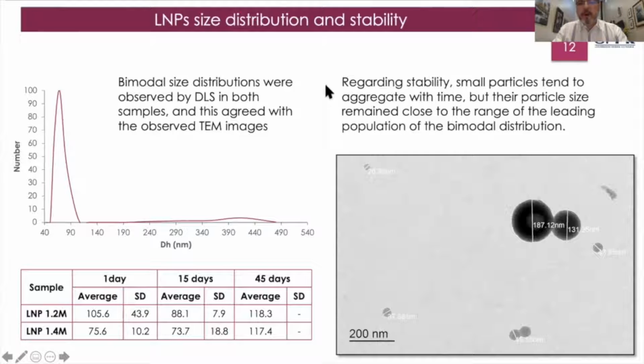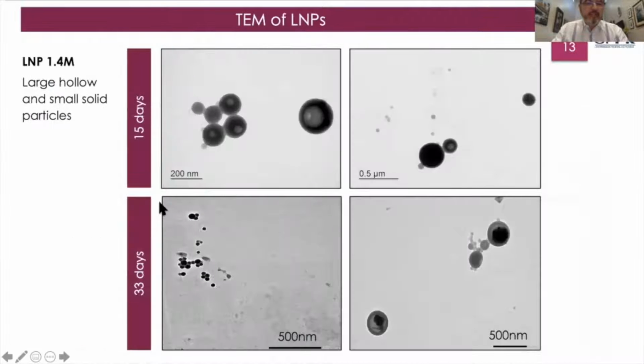Regarding stability, small particles tend to aggregate with time, but their particle size remained close to the range of the leading population of the bimodal distribution. Stability in this case, followed by DLS, was done for 1 day, 15 days, and 45 days. The transmission electron microscopy images that I show in this slide reveal the presence then of hollow particles formed probably by the expelling of the solvent during the precipitation of those lignin nanoparticles, and also after as much as 33 days of storage in suspension, the aggregation of small particles forming these lumps that could be easily taken apart by agitation.